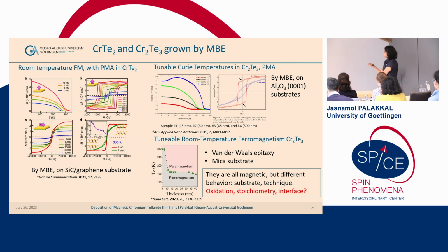So that's the main point why we have to be doubtful about the origin of the magnetic moment, if it is really from the lattice of the chalcogenide or not. And in this case, you can see even a few monolayers of CrTe2 is showing almost near room temperature magnetism, and the TC is increasing when the thickness is increased, and that's the same case with Cr2Te3. The TC is increasing when the thickness is increased.